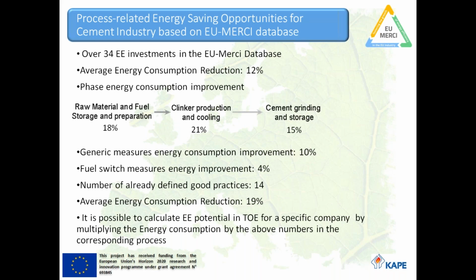When it comes to process-related energy-saving opportunities that can be identified for the cement industry, we have analyzed over 34 investments made in the enabler countries. We have found that the average energy consumption reduction of each measure was around 12%, and we could divide them into phases. So in raw material and fuel storage preparation, by investing in energy efficiency, 18% of energy consumption lowering may be expected. In clinker production and cooling phase, when we intervene in this phase, 21% energy consumption improvement can be expected, and in the phase of cement grinding and storage, 15% energy efficiency increase on average.